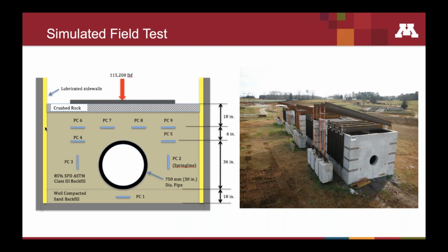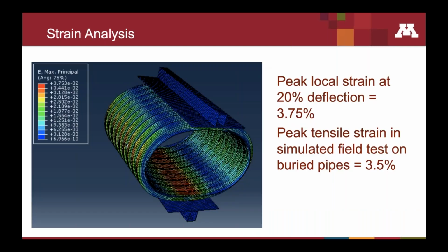This is just an image of our pressure cell that we compress the pipes in. Each of those concrete weights weighed 2,000 pounds. You see that there were 4 of them hanging on each chamber, and we had a 12-to-1 mechanical advantage with that loading mechanism, so we were generating in excess of 30 to 40 feet of fill on those pipes with a very poor backfill condition, so we were really stressing these pipes.